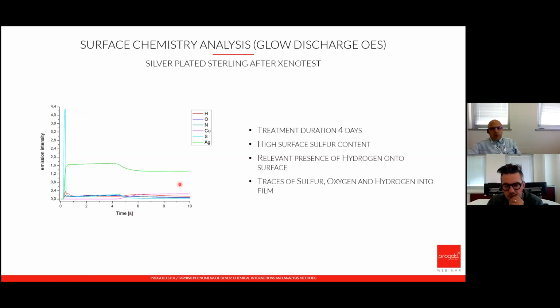Ultraviolet beams on silver-plated sterling always lead to a big concentration of surface sulfur together with a significant presence of oxygen and hydrogen at the surface, and traces of them in the galvanic coating.